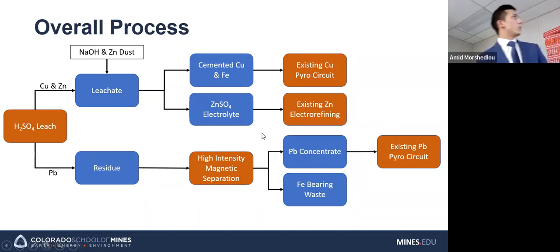To the leachate, what we're doing is we're neutralizing with sodium hydroxide. You could also use soda ash or any other basic thing, doesn't really matter. And then we're adding some zinc dust to cement out the copper and the iron. And the reason for that is iron causes some problems later on in processing. If we can get it out of the leachate, it just makes it easier. That's due in large part to the multivalency of iron. It makes other processing kind of difficult.